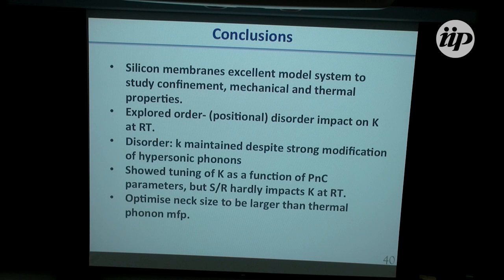And this basically means that one has to optimize the neck size and make it larger than the average phonon mean-free path. That's very important. So the neck size, because we still were not very clear exactly how the propagation happens, right? There is one picture that is using waves, as in photonic crystals. Other pictures using ray-type optics to show the motion of the phonons. We need to understand a little bit how the propagation actually takes place. But empirically, it's very important to have this neck, this amount of material left between holes, to be larger than the thermal phonon mean-free path, the average.